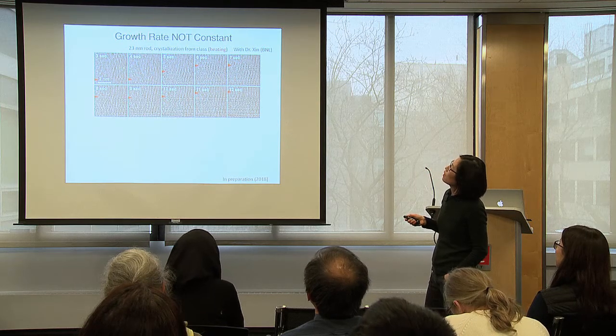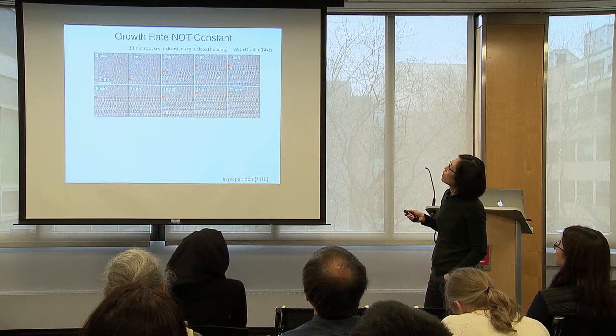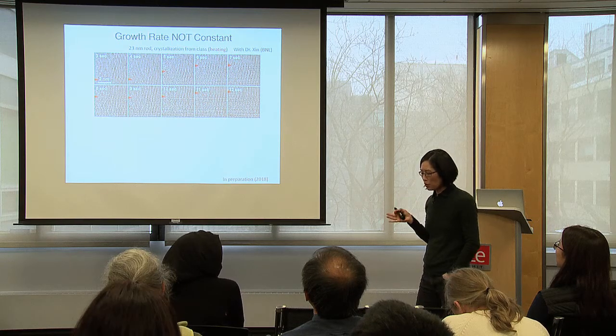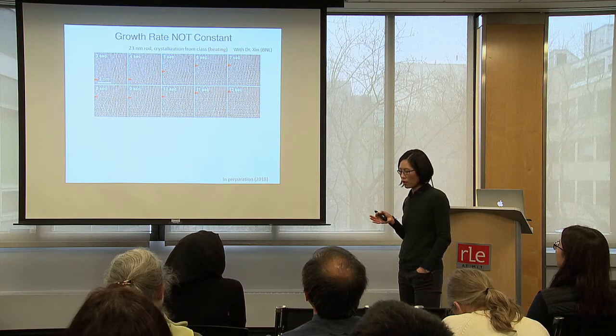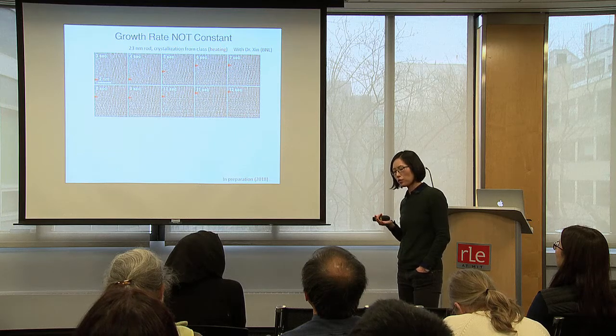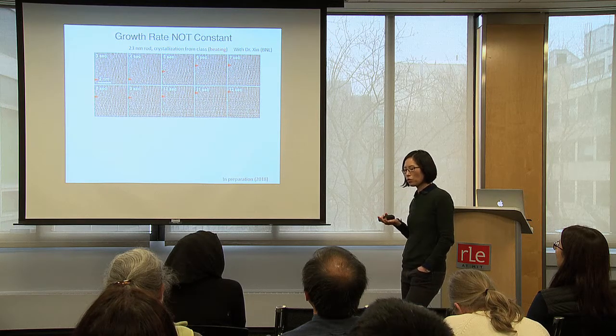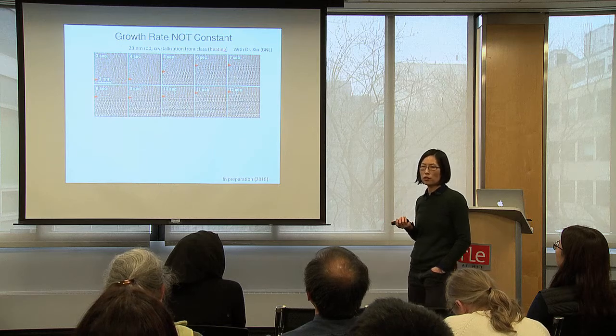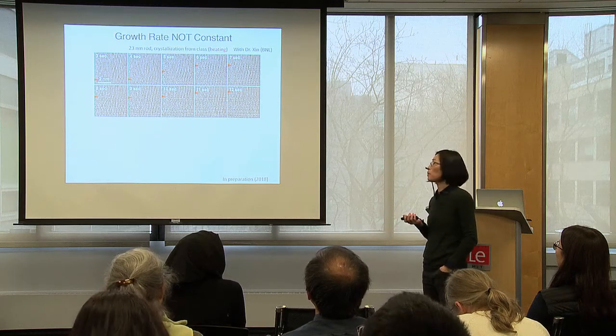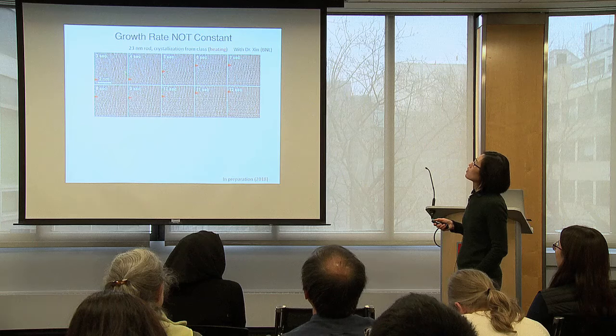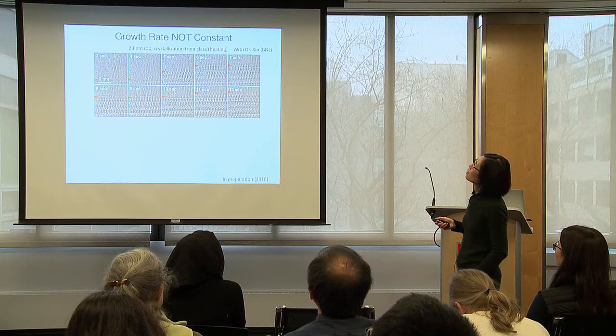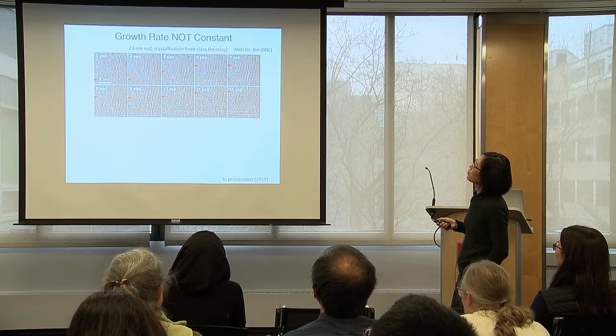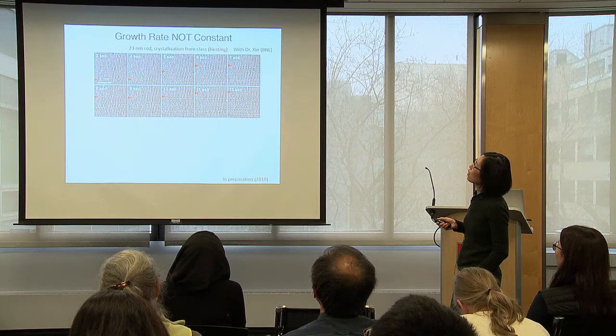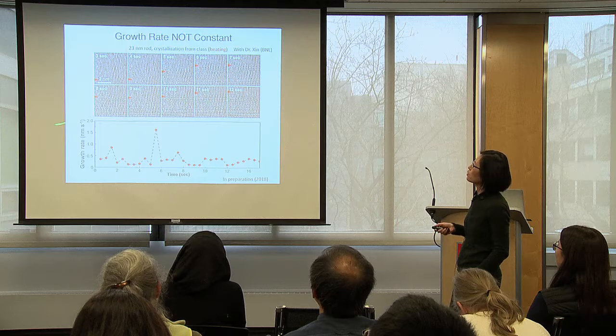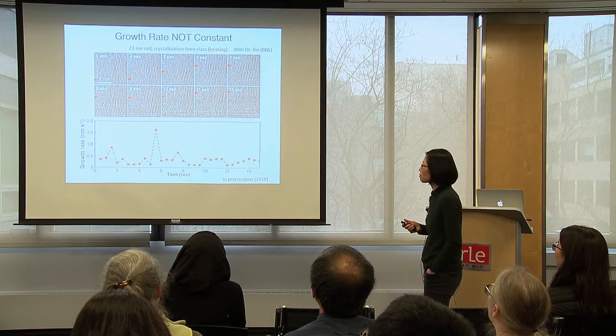Okay, so here is now just the time snapshots. So what you see is that even though this is isothermal, the growth rate is not constant, right? If it's purely diffusion controlled, growth rate should be constant because diffusion is constant at the same temperature. So the growth rate is not constant. Okay, this is a 1 second time difference. Not only is it not constant, it seems that suddenly it jumps and then it kind of gets stuck and then it jumps again. Okay, so there's a little bit of fluctuation.